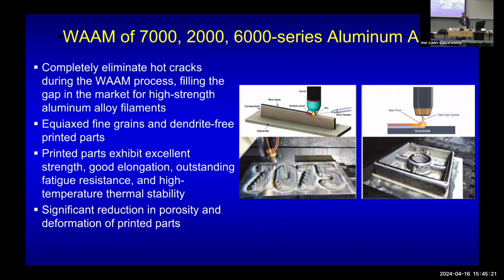But with our nanoparticles, with our nanotechnology, we can completely eliminate hot cracks. There's no problem. And no matter how thick a layer you build up, the nanoparticles always control the grain to equiaxed fine grain, almost dendrite free. So for us, we don't care how many layers you build up. We don't worry about dendrites. We do not worry about columnar growth, because the nanoparticles block them. Printed parts can also have high performance, with a significant reduction in porosity and deformation of printed parts. So I will not go into details. The reason is we can also control residual stress and distortion.